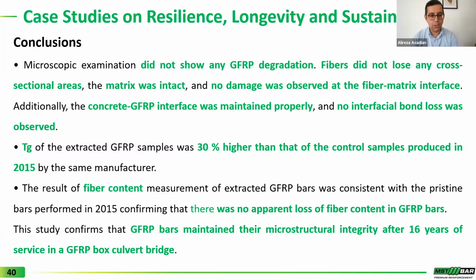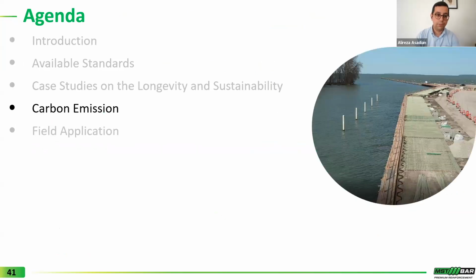Interestingly, they observed that the Tg of extracted GFRP samples was 30% higher than that of a control sample produced in 2015 by the same manufacturer. Also, similar to the previous study, in the result of fiber content, there was no apparent loss of fiber content in GFRP bars. And finally, they concluded that this study confirms that GFRP bars maintain their microstructural integrity after 16 years of service in a GFRP box culvert bridge.